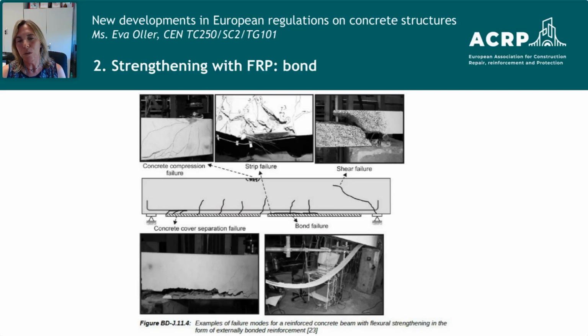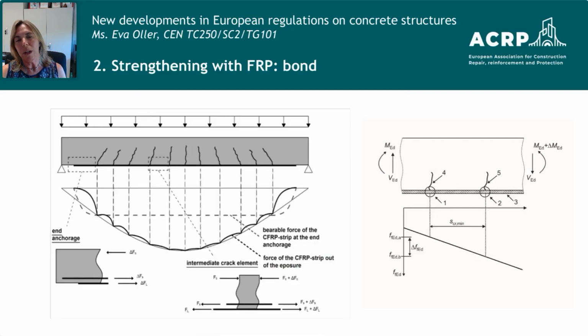The only point is that in most of the existing research, it has been observed that by bonding this type of laminate, we can reach a brittle failure mode, which consists of the debonding of the laminate at the laminate end or initiated between cracks, which is called intermediate crack debonding. So during design, we should check that this type of failure is not going to occur. For this purpose, we need to check the end anchorage.